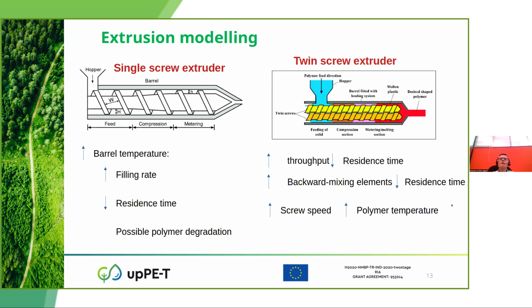The barrel temperature also influences the residence time in twin screw extrusion. In twin screw extruders, the throughput has significant influence on the residence time. A higher throughput decreases the mean residence time and the width of the residence time distribution. The influence of the screw speed on the residence time is rather low, and backward mixing elements have a high impact on the residence time, and the distribution increases.